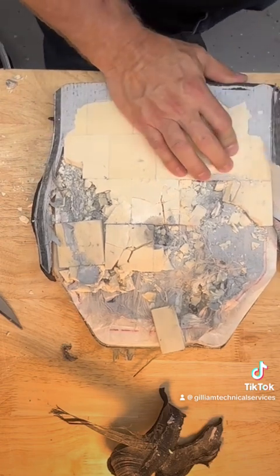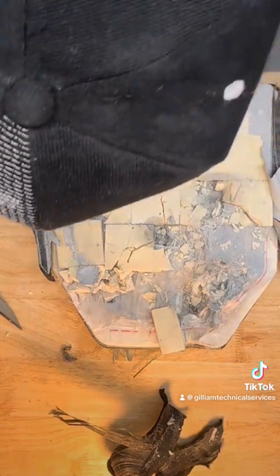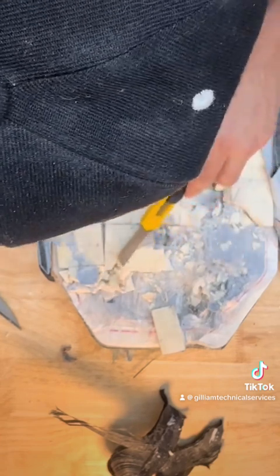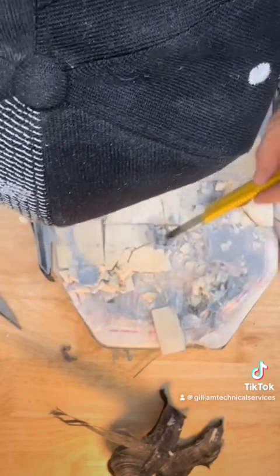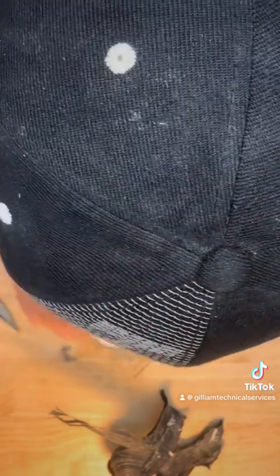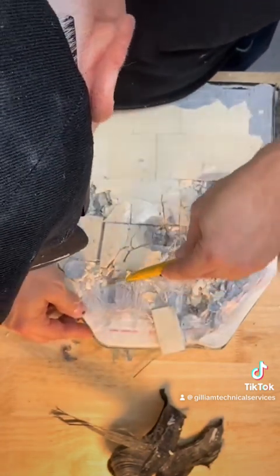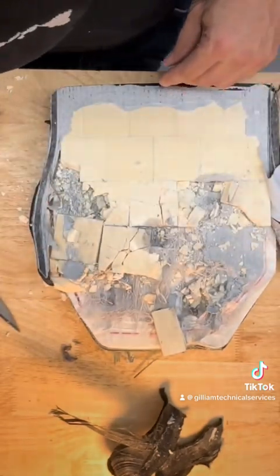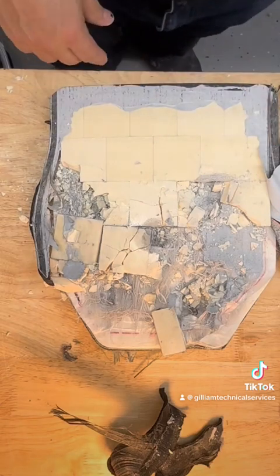It's amazing how close these shots were placed together, and yet you still have no penetrations. You skipped a tile here, but here, here, and here were almost adjoining. These two were adjoining tiles, and these two had one tile of separation, and these two had one tile of separation. Very, very good result — very impressed. You can see how the adhesive between the tiles also does a good job in resisting multiple hits.